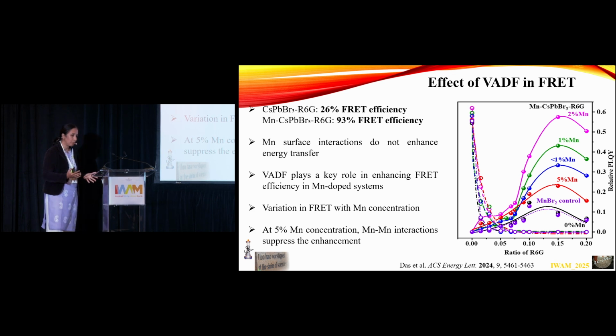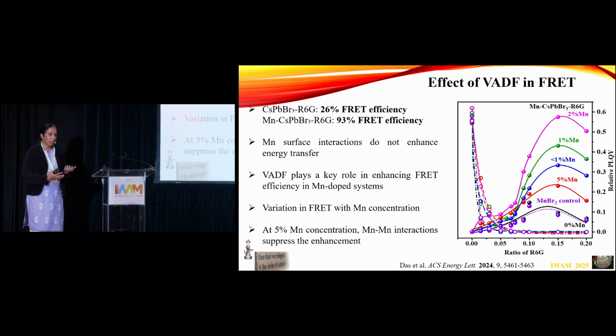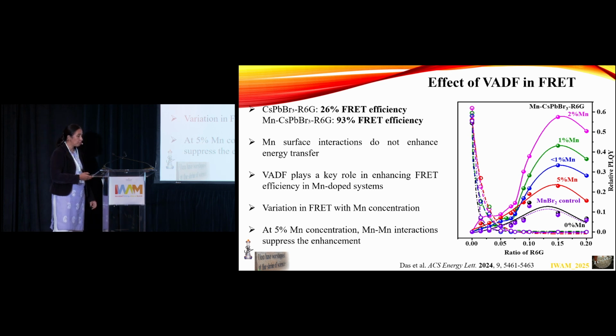That's not very surprising though, because by that time you have a manganese-manganese interaction. We are not interested in manganese-manganese interaction. We are looking at interaction between manganese and the host. So if you have manganese-manganese interactions, then it's going to kill this variation. And you can see here that wherever that efficiency is very high, it also keeps increasing to higher and higher ratios of R6G, suggesting that there is no self-absorption problem.